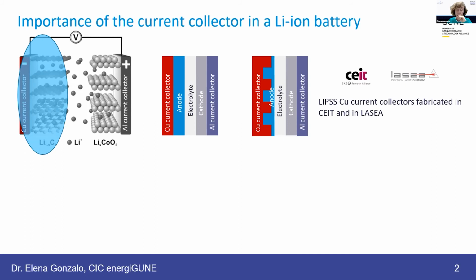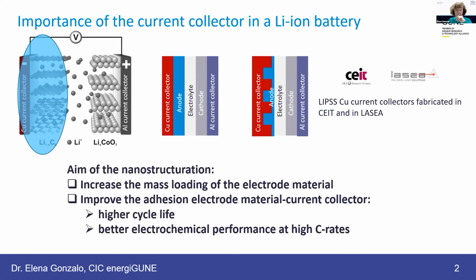I will be only focused on the anode material, although as David was saying, they have done an excellent work also in aluminum current collectors, but the main part of my talk will be only copper current collectors. So the aim of this nanostructuration was, on one hand, to increase the mass loading of the electrode materials, and on the other hand, to improve the adhesion between the electrode material and the current collector. If we do that, we will be able to have higher cycle life of the battery and better electrochemical performance when we are playing at high C rates. I will explain it to you a little bit later.